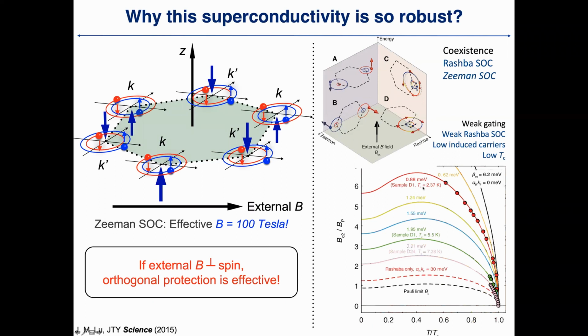So in our system, for the lower TC, like TC of 2.3 Kelvin, we are actually having a stronger protection. With increased TC, we have a more robust system with higher TC, but actually we are having a lower upper critical field due to the increased coupling between the Rashba effect and the spin and external field.